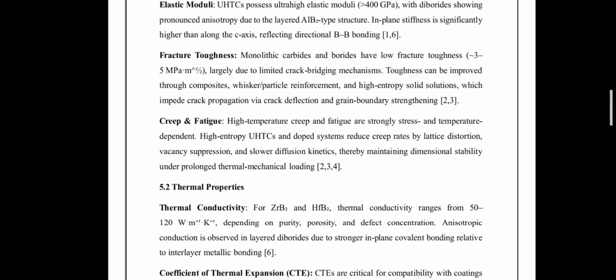Next are the thermal properties, thermal conductivity and anisotropy. Diborides such as zirconium boride and hafnium boride exhibit relatively high thermal conductivity, which depends upon purity, porosity, and defect concentration. Their layered crystal structure produces anisotropic heat transport, with higher conductivity in the basal plane than along the c axis. Defects, vacancies, and porosity increase phonon scattering, reducing thermal transport efficiency.